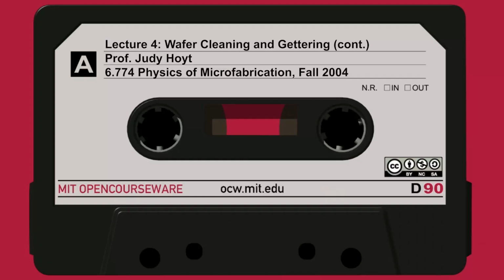So on slide 16, we talk a little bit about how extrinsic gettering can take place. Usually in the extrinsic case, people try to form these sites on the back side of the wafer, and there are a number of ways of doing it. Some very crude: grinding and sandpaper. Sometimes you'll look at the back of a wafer, especially an older wafer, and there's this ground sort of pattern, almost like it was put in a lathe, and it goes around this pattern on the back side. That was intentionally ground into the back of the wafer to make a lot of these gettering sites.